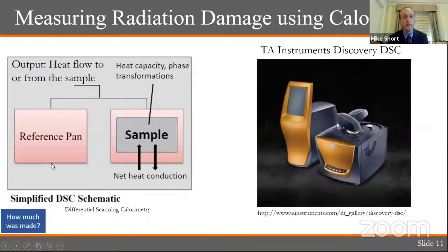The instrument that we use to make these measurements is called a differential scanning calorimeter, or a DSC. At its essence, it's a heat capacity measuring machine. It measures the amount of heat that materials absorb as they rise or fall in temperature. And the way it technically works is you have a sample in a little aluminum pan inside this piece of the DSC and an empty pan of roughly the same mass. And you measure the amount of power required to keep the two pans at the same temperature. The pan with your sample in it has more mass and therefore is going to absorb more heat when you try to heat it. So now I want to show you what these signals look like.